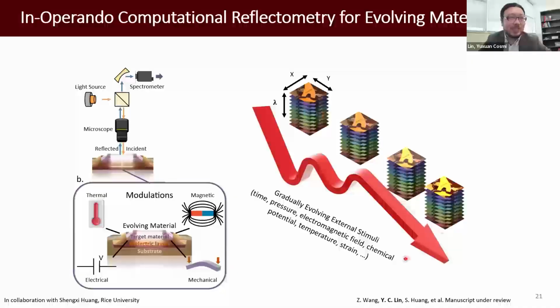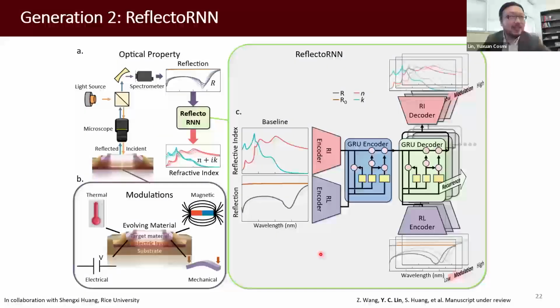So now we are dealing with this 4-dimensional data. For each image, we have X, Y location and a wavelength lambda, and this image cube is evolving with time by certain external excitations. In order to deal with this data set, we designed this RNN-based neural network. It includes some autoencoder to deal with the refractive index and the reflectance spectrum. And we use a reference refractive index, for example, the starting point of the refractive index of this material, as the input. And then we input the series of reflectance we measured during the changing of the external excitation. And the prediction is how this N and K evolve with those excitations.